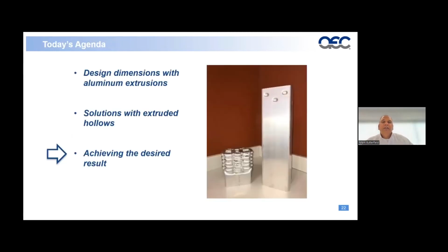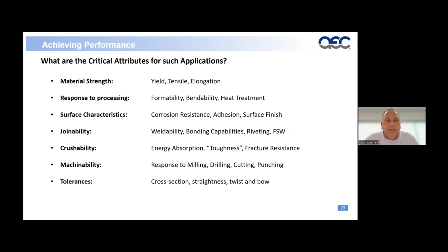So now, achieving the desired result, as we mentioned, it's the geometry of the profile. It's certainly the alloy and the characteristics of the alloy, but it's also the process that's utilized. And what we're looking for, as we design the cross-sectional profiles, and we apply the different alloys and we develop the alloys, is material strength, so TY and E obviously is where we start. The response to processing, a lot of the profiles we saw, formability, bendability, the ability to heat treat specifically to a certain temper is absolutely critical.